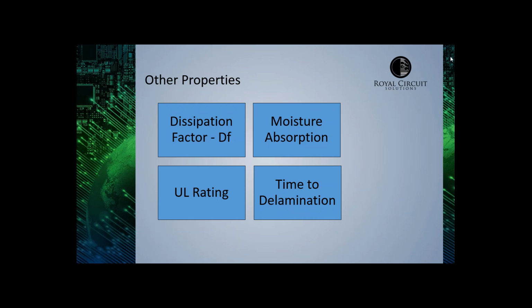Moisture absorption is more of an environmental factor, and that's the tendency of a material to absorb moisture from the surrounding environment. This will also then affect its other properties like the dielectric constant and the glass transition temperature. There's some that absorb very little water, and then others like polyimide that really seem to suck it in. UL rating is the laminate flammability. UL just stands for Underwriters Laboratories, and pretty much every material has a different rating.